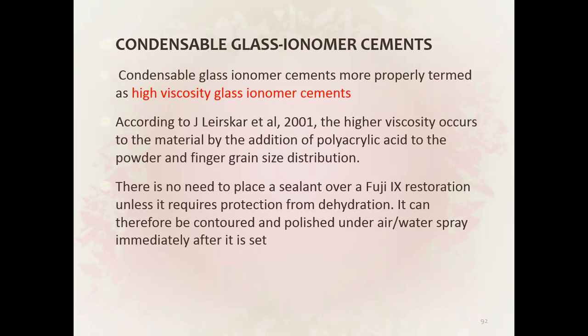Condensable glass ionomer cements, more properly termed as high viscosity glass ionomer cements. According to Leirskar et al. 2001, the high viscosity occurs due to the addition of polyacrylic acid to the powder and finer grain size distribution. There is no need to place a sealant over a Fuji 9 restoration unless it requires protection from dehydration. It can be contoured and polished under air or water spray immediately after it sets.